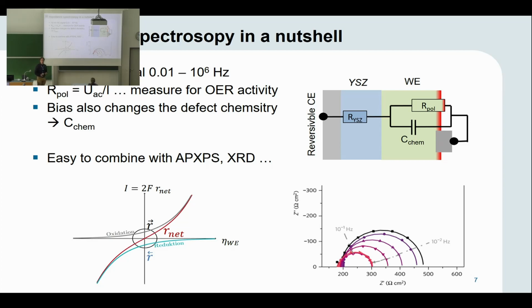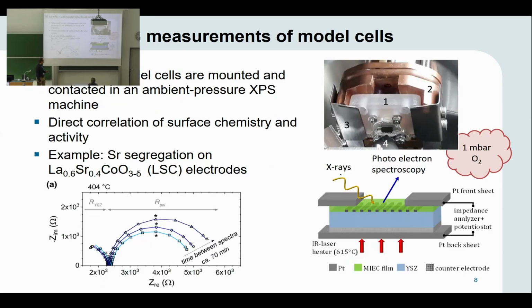Furthermore, electrochemical impedance spectroscopy is a quite simple technique. It only requires 2 electrical measurement wires, in some cases also 3 or 4, attached to the sample. So it can be easily combined with other experimental techniques as long as we can fit wiring onto our sample in the experimental chamber. And one very powerful tool to further investigate the surface properties, which are decisive for the kinetics, is ambient pressure XPS combined with solid-state electrochemistry.